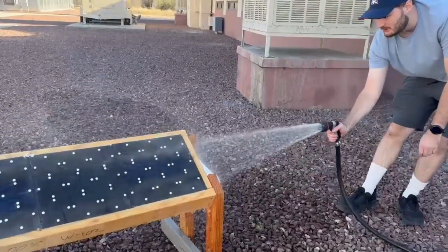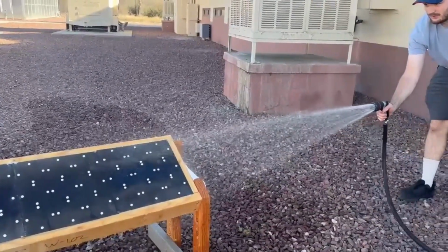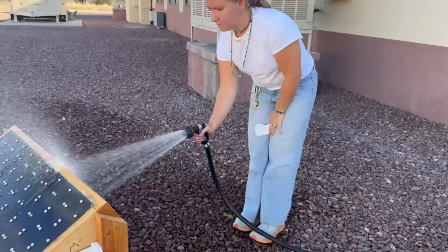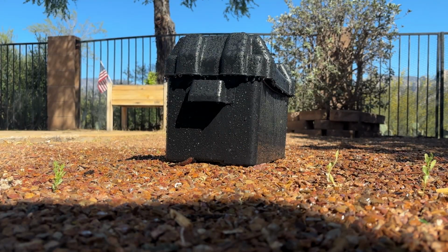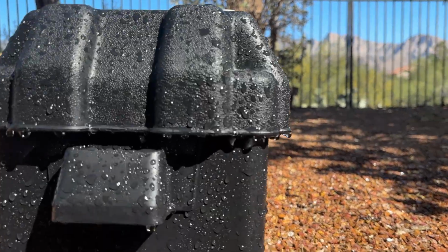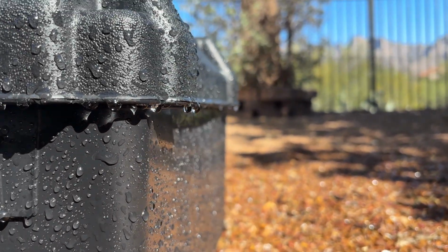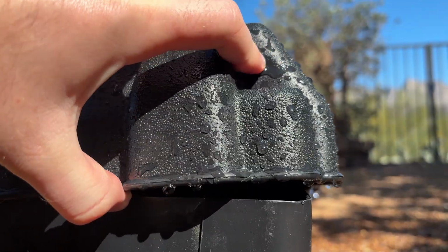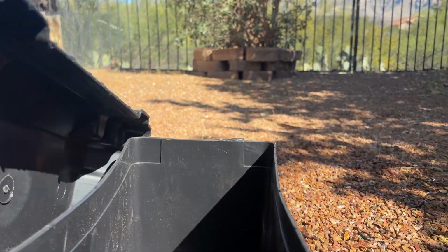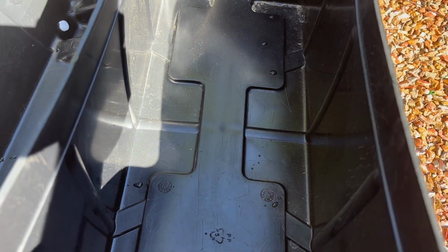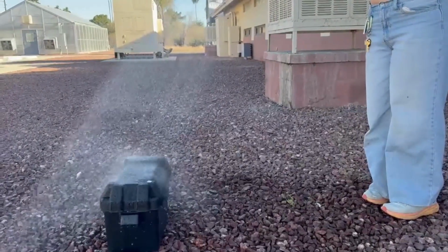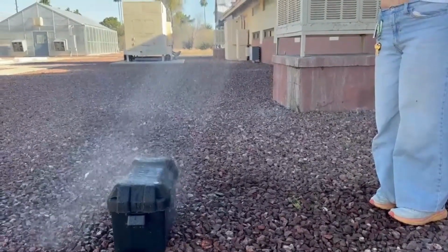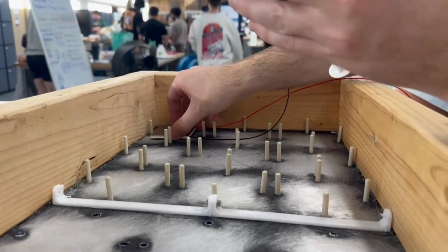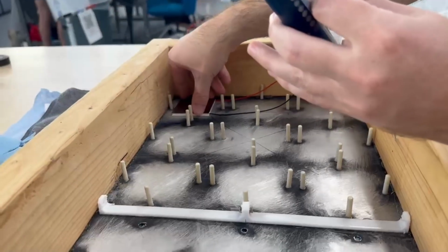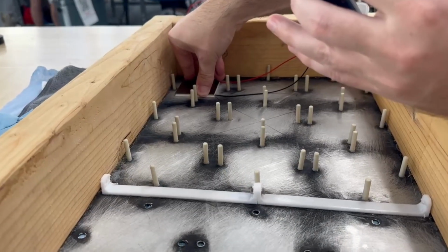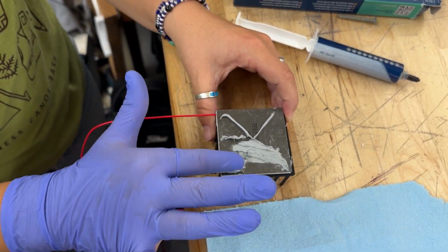The environmental operations test consisted of spraying the frame, battery, and electronics housing with a hose from various angles to simulate rain. These all passed with no issues, aside from a slight oversight in the battery housing procedure, which allowed water to drip in from the edge of the lid when checking for water intrusion after the test was complete. This was resolved by adding a step in the procedure to dry around the edge of the lid before removing, which allowed the test to pass. Now that the environmental operation test had been completed successfully, we were clear to start finishing assembling the system and adding the TEGs and electronics.